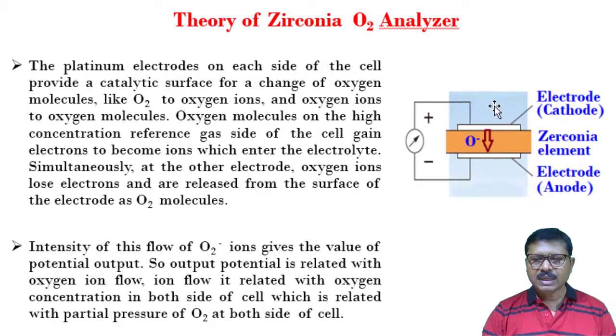So if there is a difference of concentration, there will be a difference of partial pressure at this side and at this side. Because of the presence of this difference in partial pressure, some oxygen ions will flow from one side to another, and this ion flow will ultimately create the potential difference between these two electrodes. So ultimately this potential difference created between these two electrodes is the measurement of the concentration of the unknown sample.